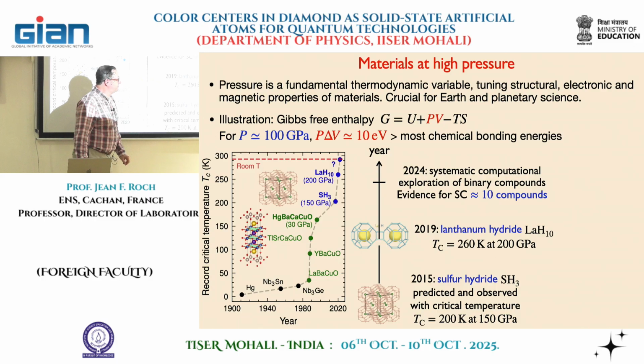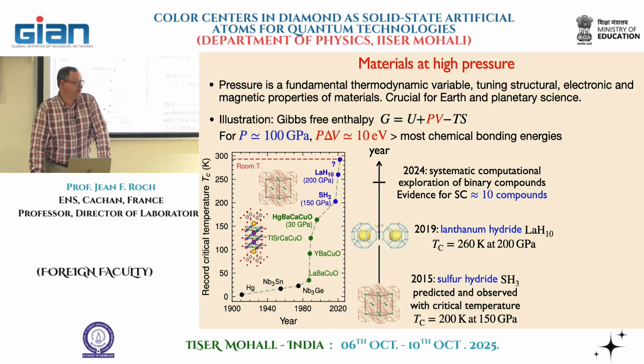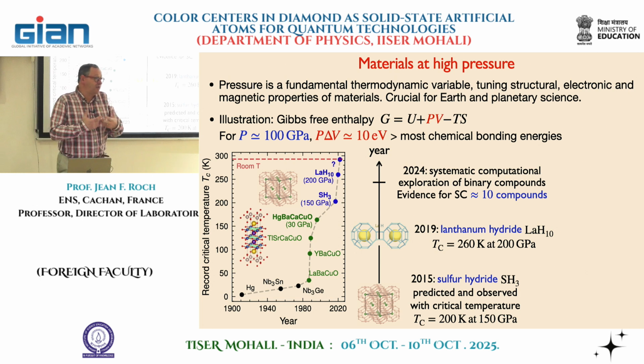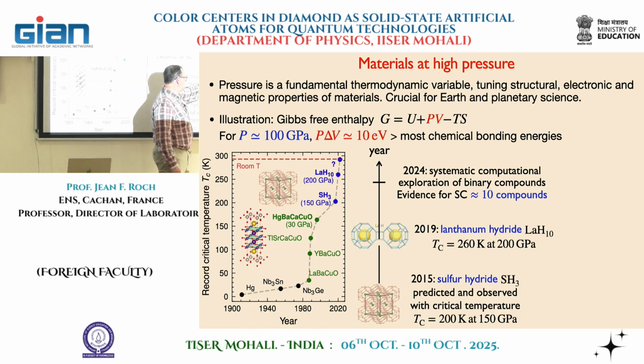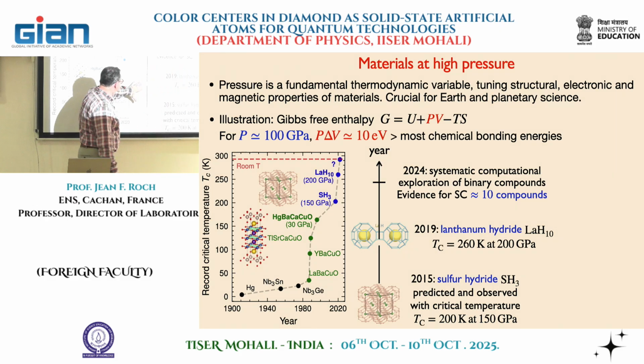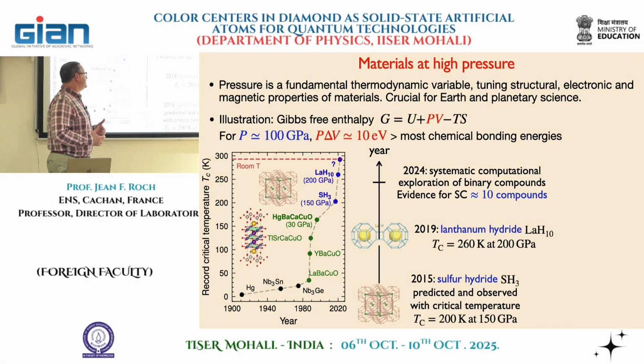And then there was another great step forward done by, again, Michael Eremets and also Russell Hemley in the US, where they observed superconductivity in another system, embedding even more hydrogen, lanthanum hydride, LaH10. And this is the structure. You see here the lanthanum atom, and around the lanthanum atom, the hydrogen atoms are organized in a cage. And this leads to physics close to the one that is expected for metallic hydrogen. The Tc is around 260 Kelvin at 200 GPa. And today, there has been a systematic computational exploration of binary compounds, and evidence for superconductivity has been found in approximately 10 compounds.